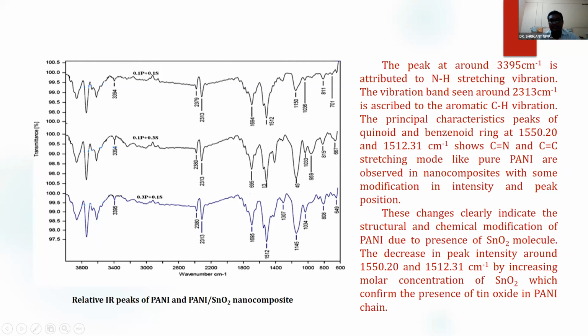But the principal characteristic peaks of the quinoid and benzoid rings, which are to be observed in polyaniline, are observed at 1550.2 and 1512 centimeter inverse, and they show because of the C=N double bond with the N and C=C double bond with the C stretching, which is just like pure PANI. That means FTIR indicates that there is PANI material, that is polyaniline, with some modification of the intensity and peak position. And this modification of the intensity and peak position is because of the addition of the SnO2 molecule.